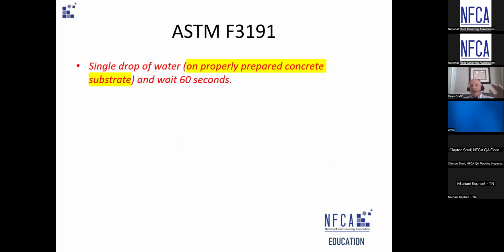Properly prepared concrete substrate. What that means, and this is defined in an ASTM, is properly prepared for whatever you're installing. So if you're installing a resinous flooring that requires an ICRI profile of 3, well, bead blast the crap out of it, and there you go. If you're doing resilient sheet and you're putting adhesive down with a paint roller, and that adhesive is good for a non-absorptive surface, clean it. Don't abrade it. Whatever prep is necessary for what you're installing, that's what you do the absorptive test on.